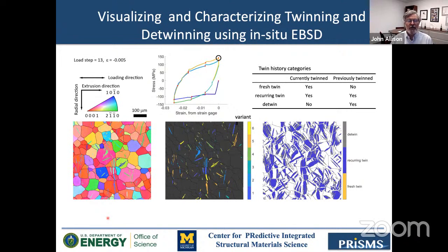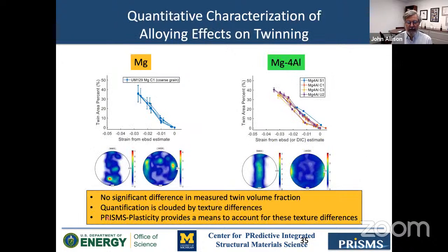We can do these same sort of experiments now in PRISMS-Plasticity, and estimate or predict the volume fraction and the variants of twins. So we've done these kinds of experiments for a couple of different alloys now. This is fairly recent results. Looking at pure mag, or unalloyed mag, and Mg-4Al. Here at 30, it's about 35 volume fraction of twins. But this is clouded, so there's no significant alloying effect on twinning.